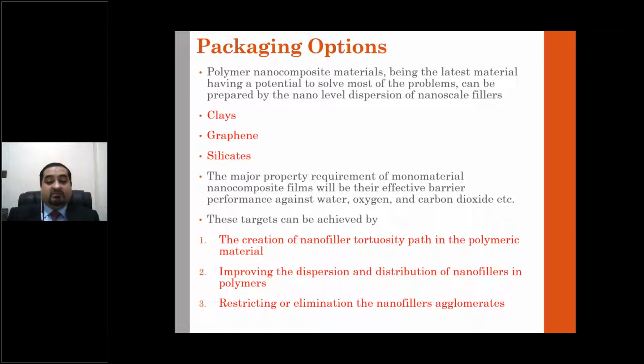and as a result of them, we always try to enhance the barrier performance against water, oxygen, and carbon dioxide. And we try to achieve these properties by making sure that we get a good tortuosity path created within the polymer by the addition of nanofiller. We get enhanced dispersion and distribution of the nanofiller, and we try to eliminate or restrict any of the agglomerates.